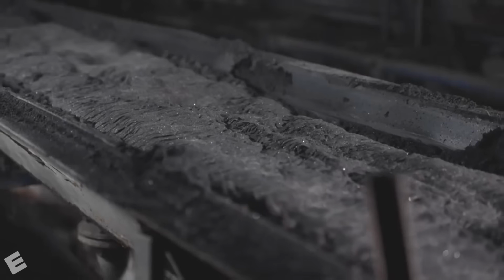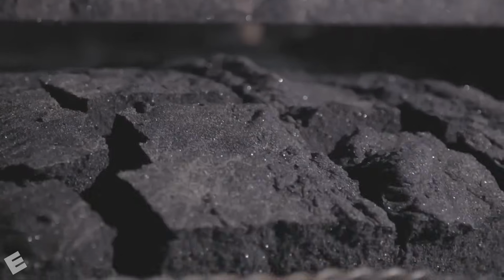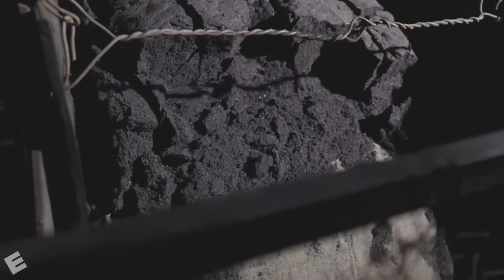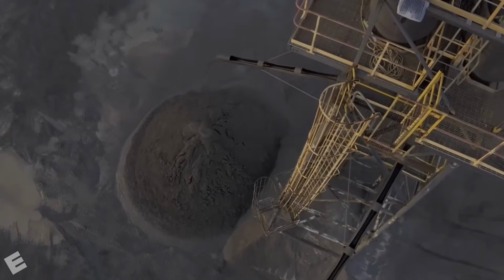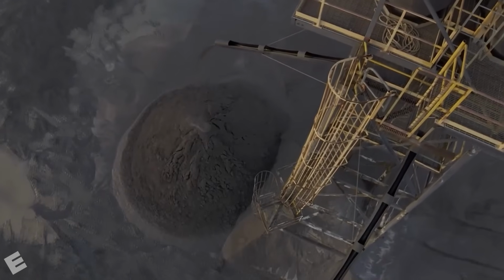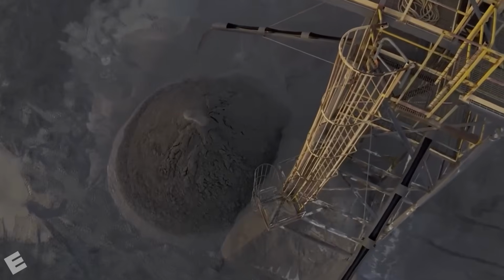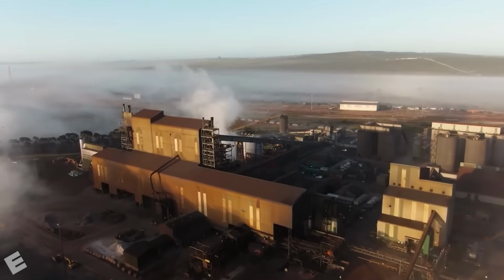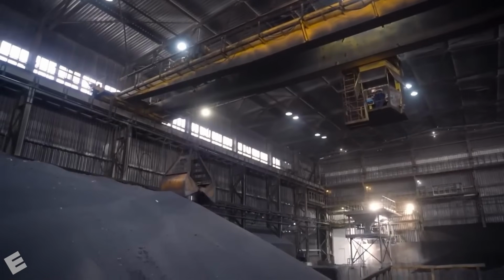After this initial separation, the mineral concentrate undergoes further purification in a facility known as a dry mill. Magnetic and electrostatic separators distinguish the minerals according to properties such as magnetism and electrical conductivity. These systems remove unwanted materials and isolate a more concentrated supply of ilmenite. Even after purification, ilmenite normally contains only about 45 to 60% titanium dioxide.